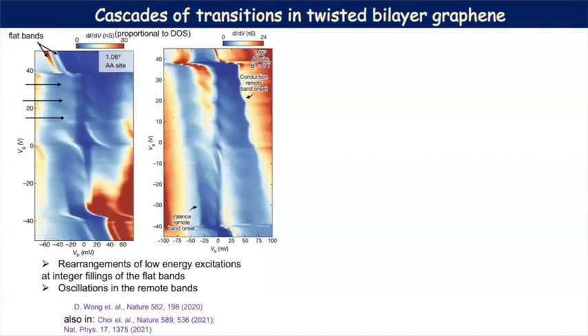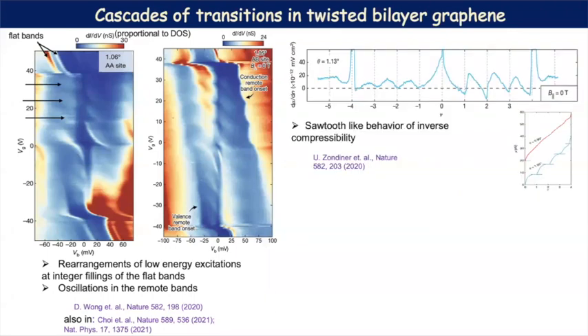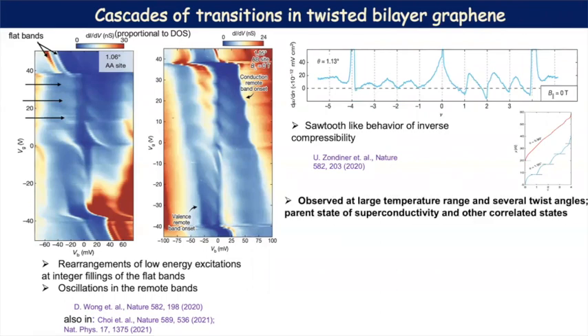Now, these cascade features have also been found in this inverse compressibility measurement, where they find this sawtooth wave-like profile with respect to doping, and we have these steps in the chemical potential. And one important aspect of this is that these cascade features have been found for a large temperature scale, which is about 50 Kelvin, which is of the order of 10 times larger than the temperature scale where we have the correlated states and the superconductivity. And we also have several twist angles over which these cascade signals are found.